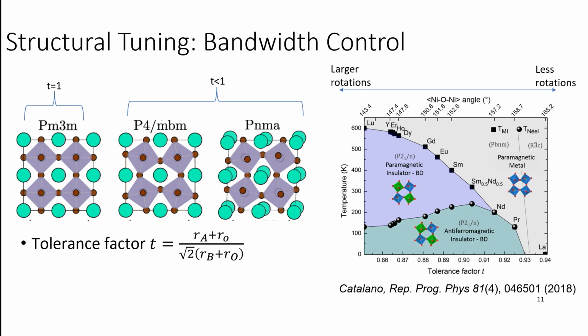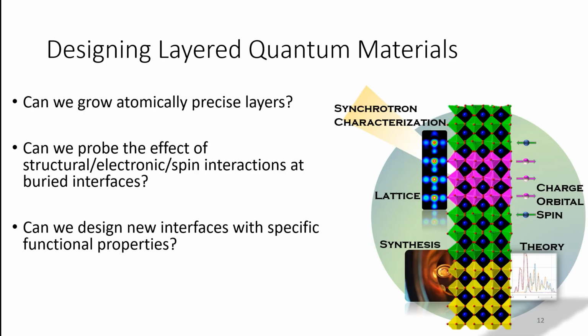The reason this happens is that a lot of the interactions, the charge and magnetic interactions, depend on the bond angle and bond distance between the transition metal ion, the oxygen, and the next transition metal ion. So as you progressively change this structure, you're effectively changing how the spins talk to each other and how easy it is for charge to move in this system to conduct current.